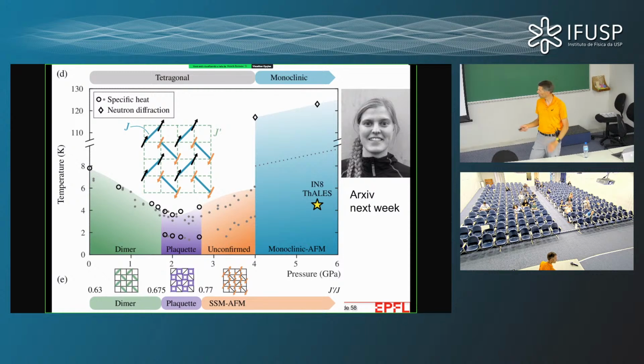They were able to go to slightly higher pressures than Julio did back in his days, but they could not apply magnetic field. We could, so there's complementarity between the two. And they report, so actually these black dots, that's Julio's measurement, the large circles are Julio's measurements, and these black dots come from this Chinese study, and they say that there's a new phase here,